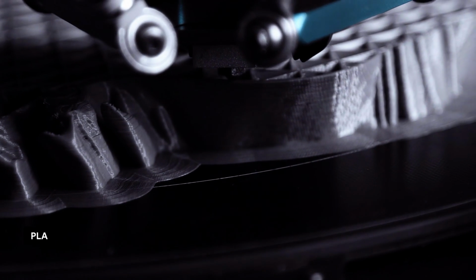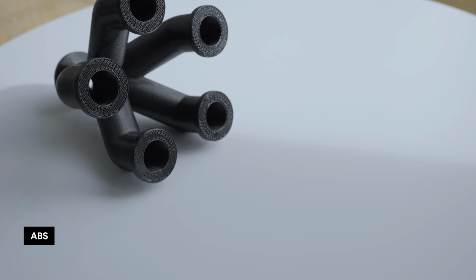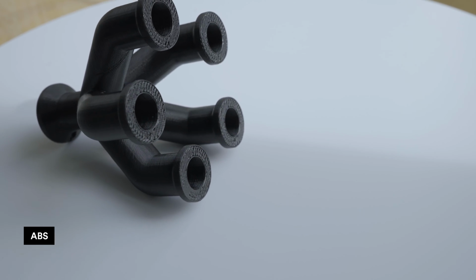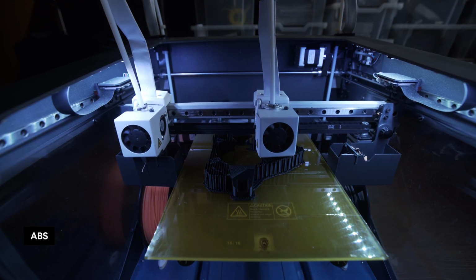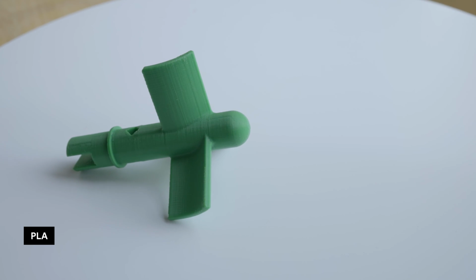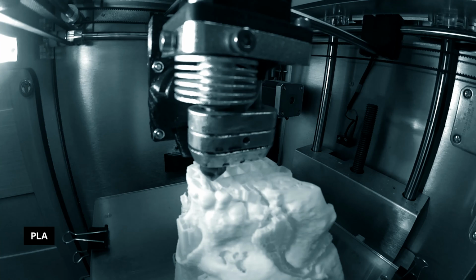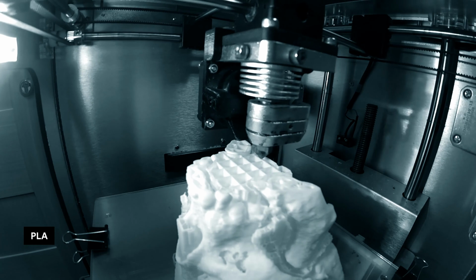PLA actually doesn't require the bed to be heated, but it's definitely recommended. The difference in nozzle temperature is less apparent. ABS is printed with a nozzle temperature of around 210 to 250 degrees Celsius, while the nozzle temperature of a PLA print is around 180 to 230 degrees Celsius.